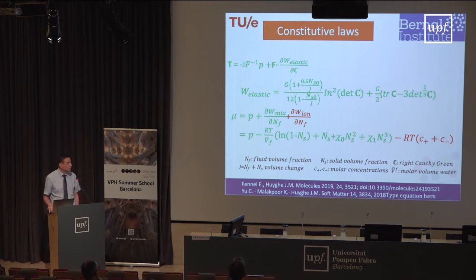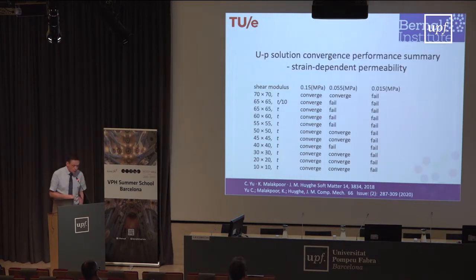And I don't want to go into the details of these equations. But what you see, if you put it into Abaqus or any other standard software, is that everything goes fine as long as you're around megapascal. Megapascal, it's okay. You manage because it converges. But as you go down, and typically this happens inside cells, at 55 kilopascal most already fail, and at 15 kilopascal you get no answer at all.